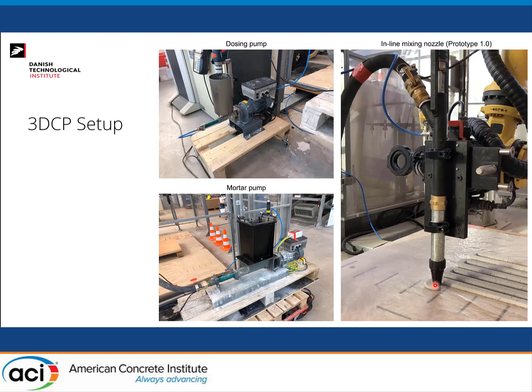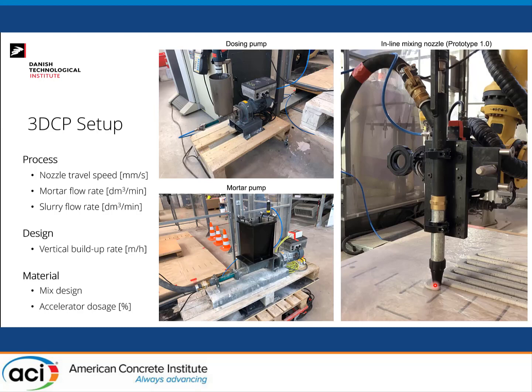So with that system, what we have to take into account as input parameters, and how to design something that could be printable or could be printed, would of course be information from the process. That means what travel speed I want to operate the nozzle at. And with that, I have to tune the mortar flow rate. I have the extrusion bead, the shape of the extrusion, and the extruded material should fit what I need if I want a wider or less wide print. And also the slurry flow rate. They have to be matched in order to guarantee I have the right amount of calcium aluminate cement and calcium sulfate slurry to activate my system.